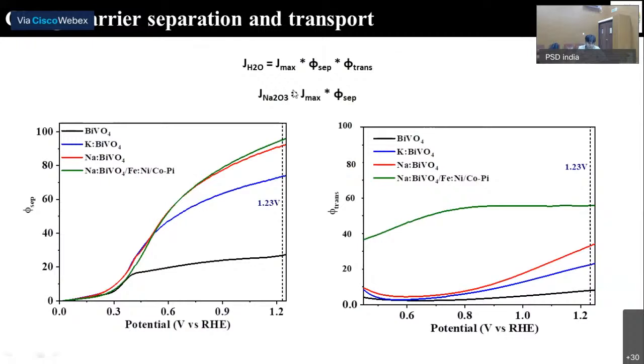So we have used these 2 equations to calculate the charge separation and charge transfer efficiency. As we can see in the first plot, that is the charge separation efficiency. With the doping of sodium atom in the bismuth vanadate, the charge separation efficiency reaches around 90%. That means in the case of sodium doped, most of the charge pairs which are generated when the light illuminates it are able to get separated.